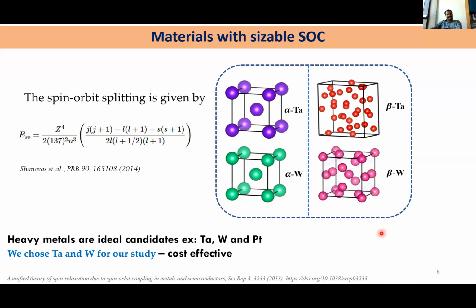Since the spin orbit coupling depends on the electron scattering with the lattice, and the lattice depends on the crystalline phase, by tuning this crystalline phase we will be able to tune the spin orbit coupling. That helps us tune the spin Hall angle, which is a key parameter that tells us how efficiently we can switch the magnetization with a small current.